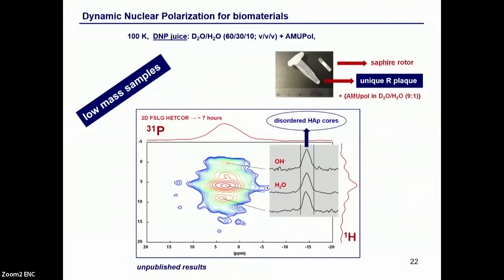And the third and last reason is you can go back to low mass experiment, as I told you. Here we are looking at one unique Randall plaque, you see, with the DNP juice, and we tried the experiment. And in fact, in 7 hours, we had this HETCOR experiment correlating the phosphorus dimension to the proton, and the signal-to-noise ratio is quite good.